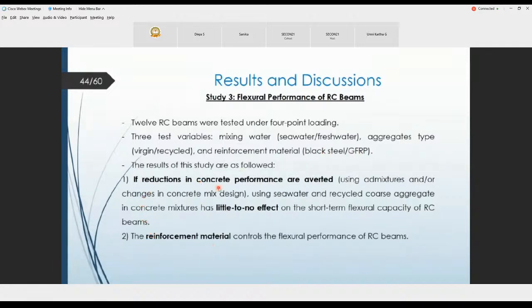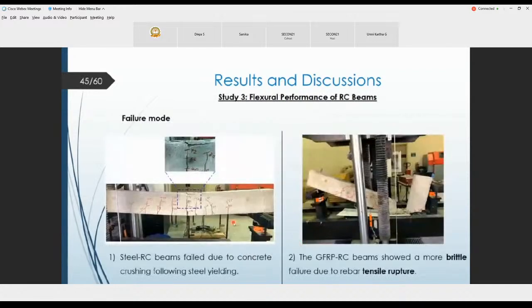If reductions in concrete performance are averted using admixtures and/or changes in concrete mix design, using seawater and recycled coarse aggregate in concrete mixtures has little to no effect on the short-term flexure capacity of RC beams. The reinforcement material controls the flexure performance of reinforced concrete beams.